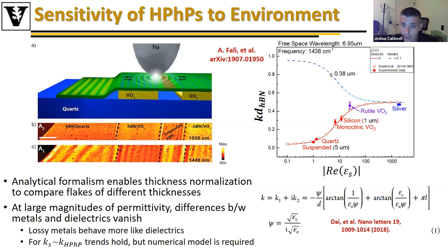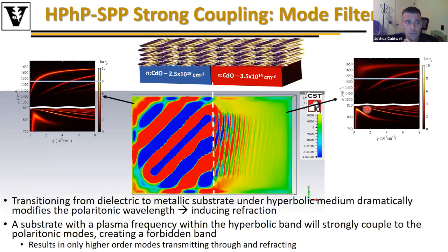In contrast, if I have a metallic substrate, we actually see that it will do the inverse of this. So it promises us the opportunity to get to really small polariton wavelengths simply by transitioning from a dielectric to a metallic regime. Now we looked at silver, but of course in the infrared, silver has such a large negative permittivity that it doesn't look any different than a dielectric with such a permittivity. And so we used cadmium oxide as the substrate, as I showed you before, and have been able to demonstrate that this significantly shrinks the wavelength, and you can control this by carrier density, which I will show maybe two slides left.